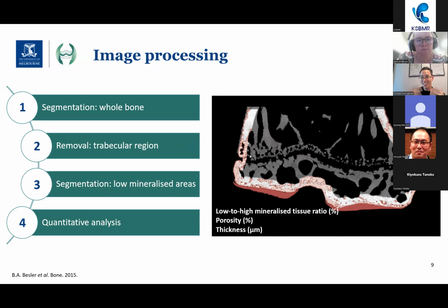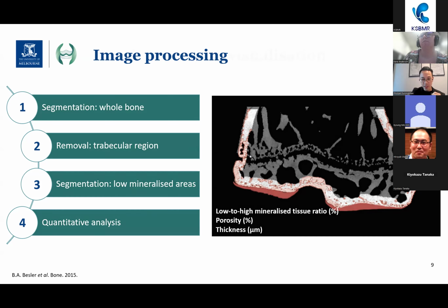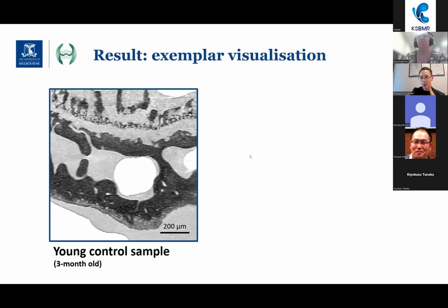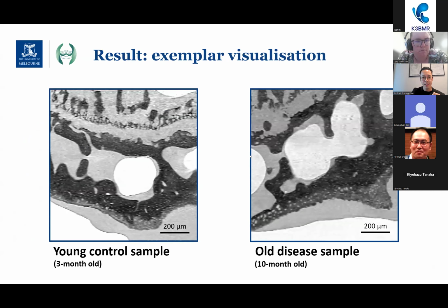Now that we have successfully segmented all these regions, we can apply the usual morphometric measures like the ratio of low to high mineralized tissue, porosity, thickness, and so on. Just to show you an exemplar visualization of what we can get: in this data set that we acquired, we used a 3 micrometer voxel size, but it can actually go all the way down to 0.3 to 0.2 micrometer, which can get you up to cellular lacunae and canaliculi visualizations.